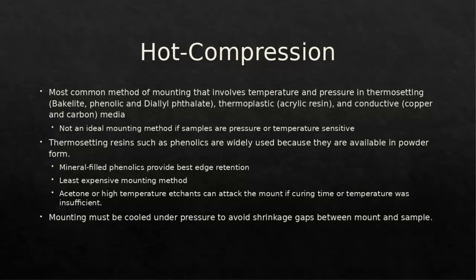The problem with the phenolics is that if you do not have them cured sufficiently, if the curing temperature and or time is insufficient, what ends up happening is the acetone and or high temperature etchants can actually attack the mount, and now you have a bigger issue with your sample.